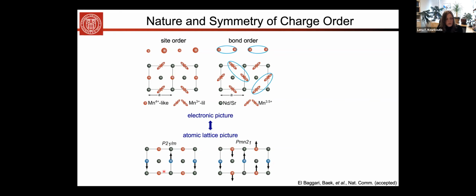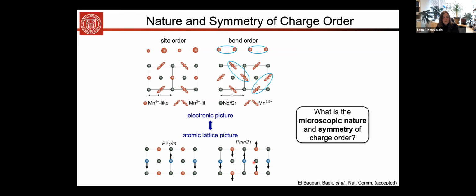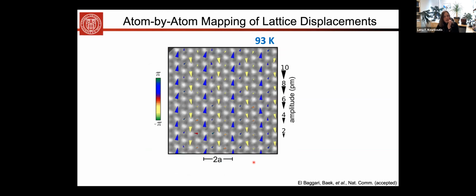So we can use this picture of charge ordering to track in real space the heterogeneity and competition between these individual phases. Okay, so skipping lots of steps, we can now look at the results at near liquid nitrogen temperature. So this is the manganite crystal, it's a thin film image at low temperature, and we are now tracking the displacement of the atomic columns at low temperature.